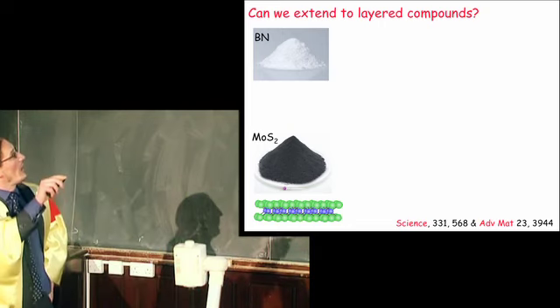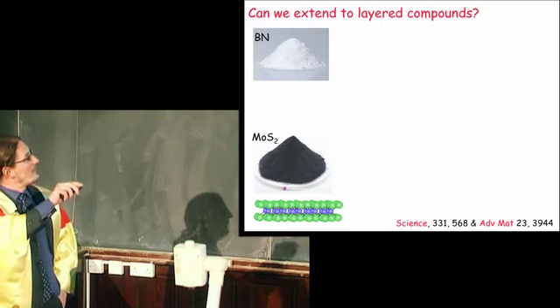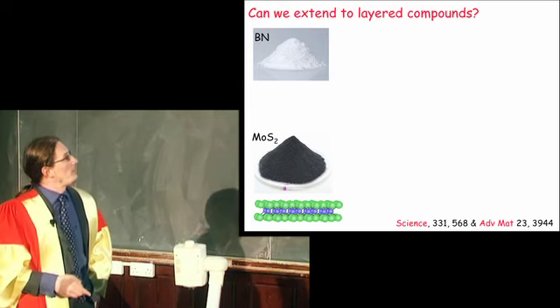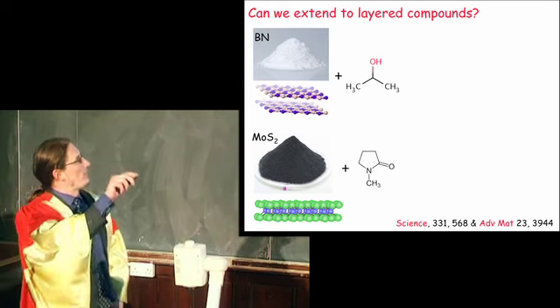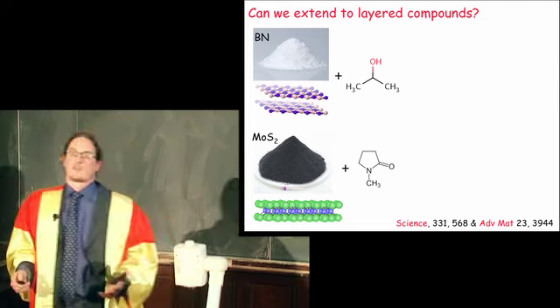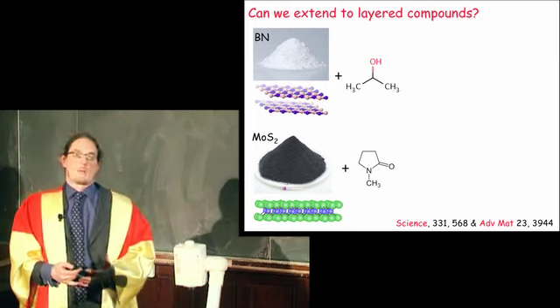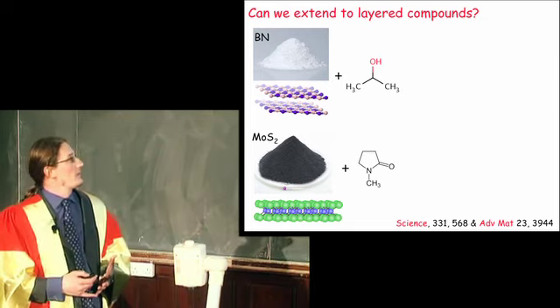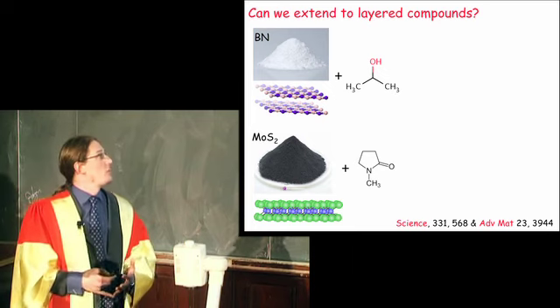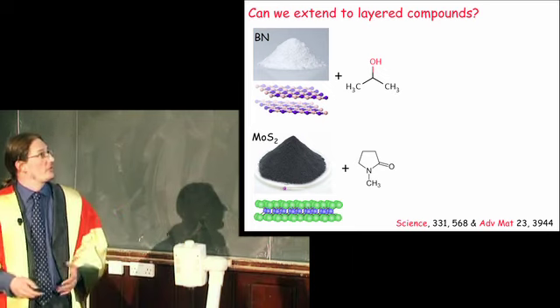Well, we take boron nitride powder, and indeed, as another test, molybdenum disulfide powder, and we sonicate them in solvents. Now, we didn't pick solvents at random. We used a combination of preliminary experiments and what we knew about the thermodynamics of the system to choose the solvents.